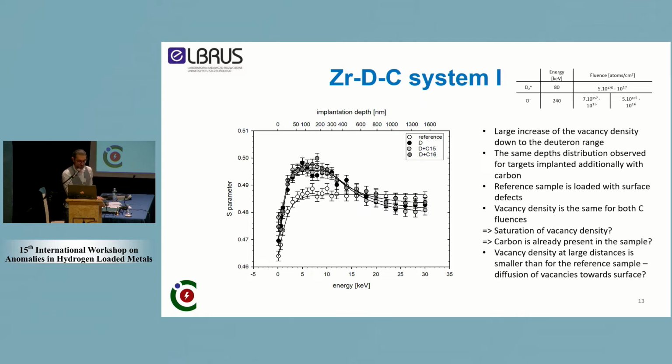Then I wanted to add that our reference is greatly increasing at the very beginning of the energy of the incident beam. This is due to the metallic state of the original sample that we're using. Hence, I hypothesize that this is due to lamination defects and dislocations generated by lamination on the very surface of the material.